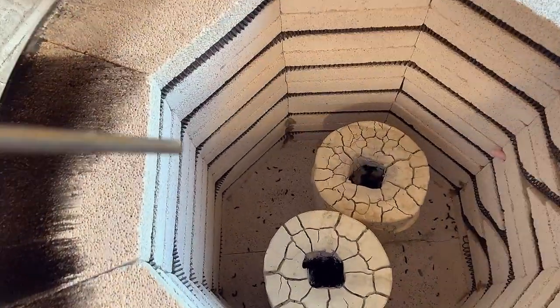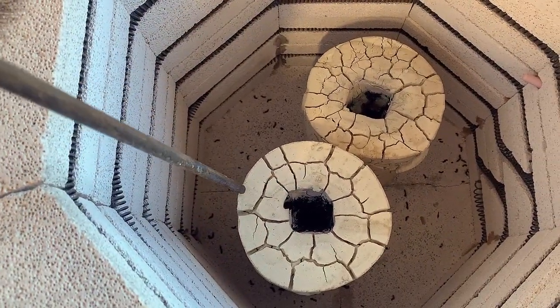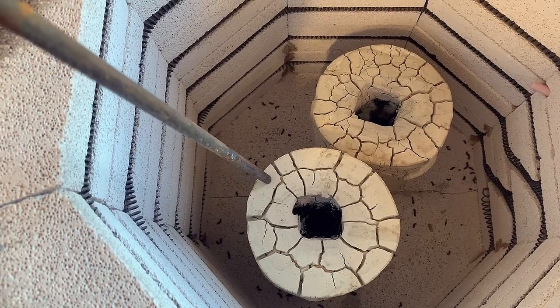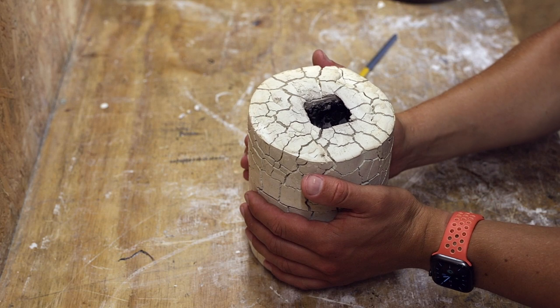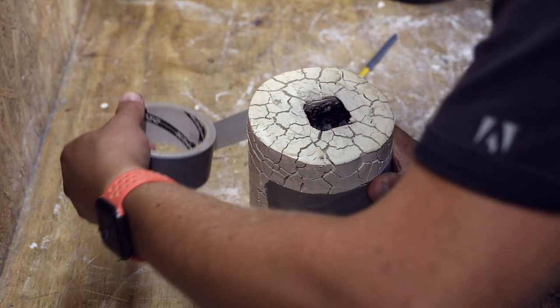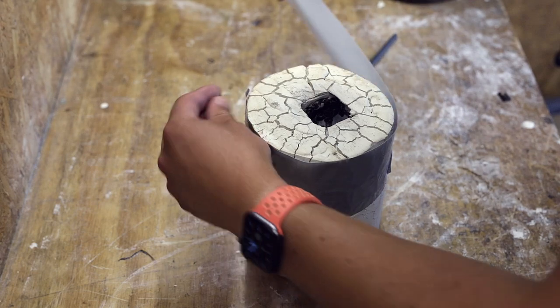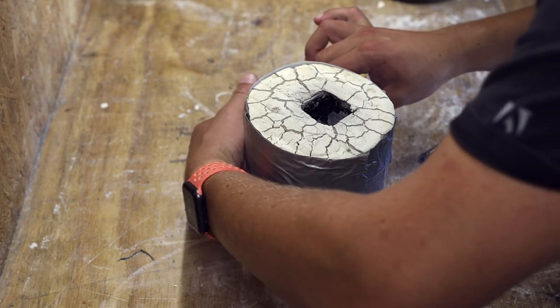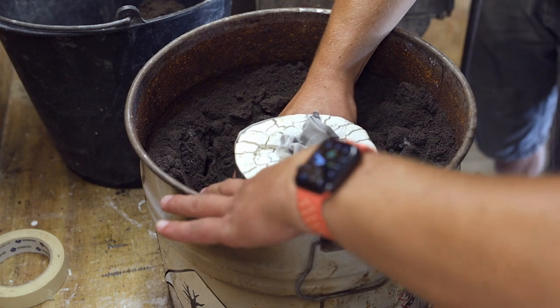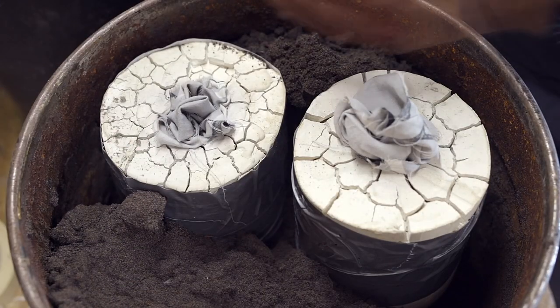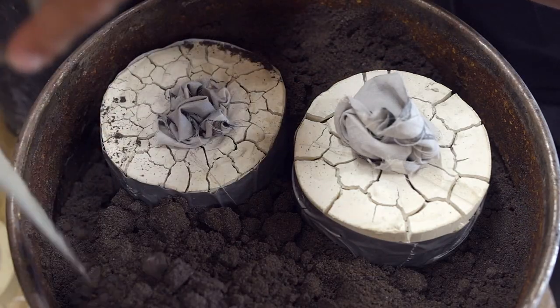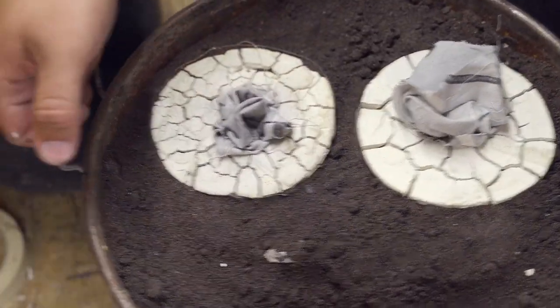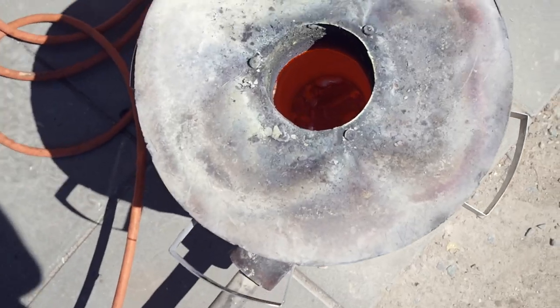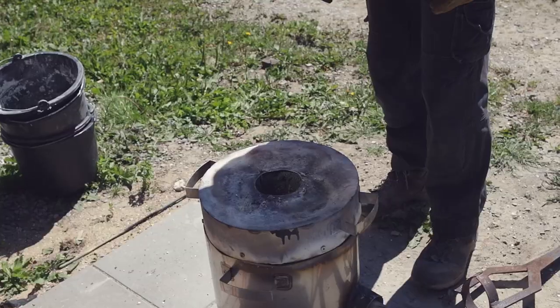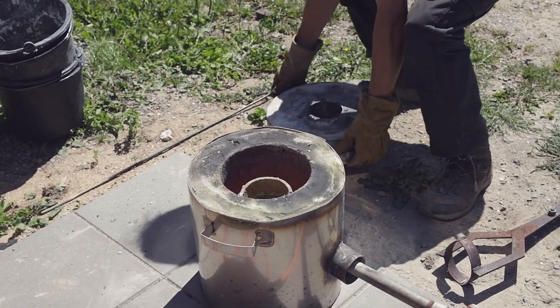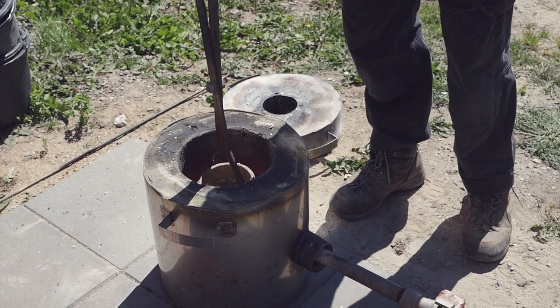I was quite disheartened when checking the molds after the burnout cycle has finished. They both had cracked severely and I thought they both had failed. But I decided to continue with the help of my trusty friend, more duct tape. To support both molds further, they were surrounded by some casting sand in a metal bucket. And in the meantime, Sebastian had prepared a good portion of molten brass, which had a lot of oxidized zinc floating on top. This is easily skimmed off just before casting.